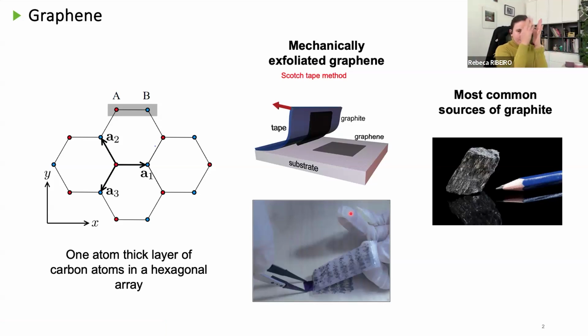So, okay, we have a big piece of graphite. We take Scotch tape, we put the graphite on top of this Scotch tape, and we peel enough until we obtain, as you can see in the picture, so my pointer is really bad. Ah, there it is. Until you obtain a kind of thin layer of graphite on your Scotch tape, and then you deposit it on a substrate. However, not every substrate can be used for this.